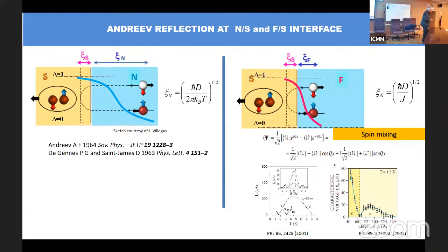But we should be able to tell if there is a zero pi transition. I see. And how far above the critical current can you go and still feel it? No, this is tricky. If you go way too far above the critical current, you lose this. You cannot measure the resistance change. You may be above at a level that you can comfortably measure, but still feel the modulation of the resistance due to the changes in the critical current. Okay, but you have to look for it.